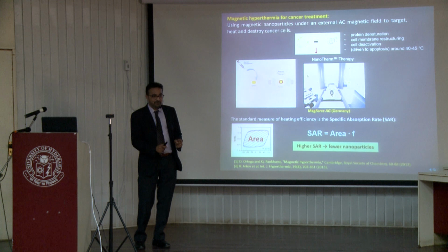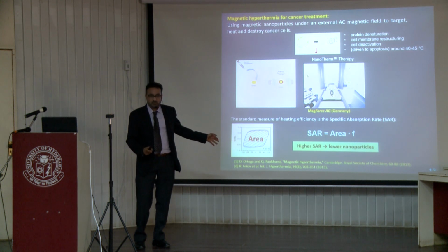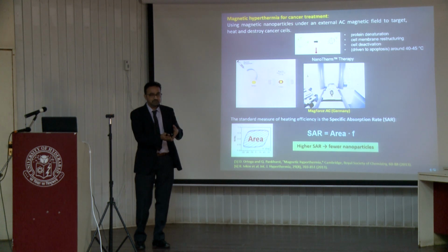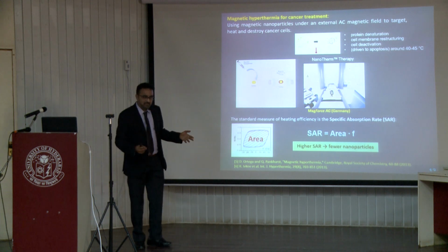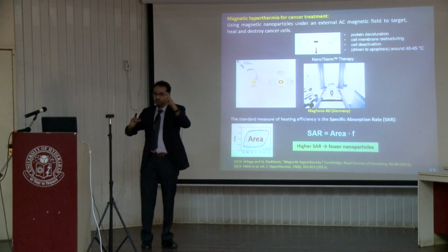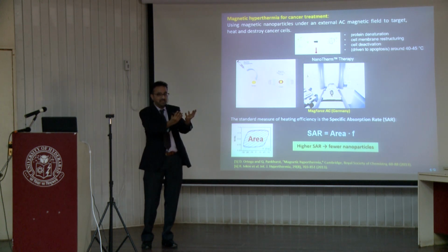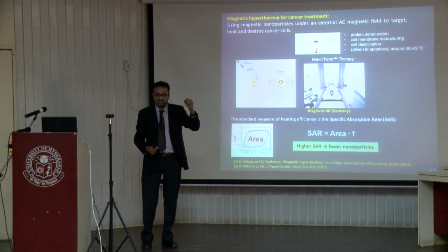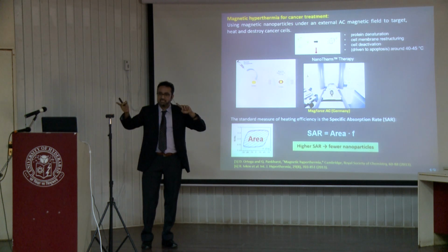The difference is that DC hysteresis loops for nanoparticles, especially for the 20 nanometer particles that we work with, will be zero. There will be no coercivity. There will be no hysteresis because these are superparamagnetic. And when they're superparamagnetic, you can think of each nanoparticle itself being a ferromagnet, a super spin. It's a collection of all these spins. It's a ferromagnet by itself. It has a large magnetization. But then there's no correlation between neighboring particles, so they're all randomly fluctuating at high temperatures.